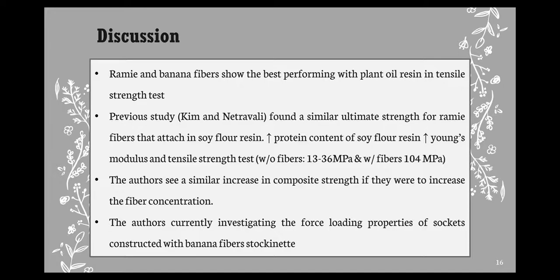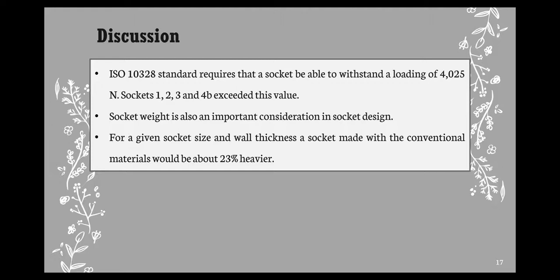The authors are currently investigating the force loading properties of sockets constructed with banana fiber stockinette. This study only tested the ramie fiber, and the other study the authors are working on uses the banana fiber stockinette. Also, the ISO 10328 standard requires that a socket be able to withstand a loading of 4 kN. Sockets 1, 2, 3, and 4B exceeded this value. Socket weight is also an important consideration in socket design. For a given socket size and wall thickness, a socket made with conventional material would be about 23% heavier.